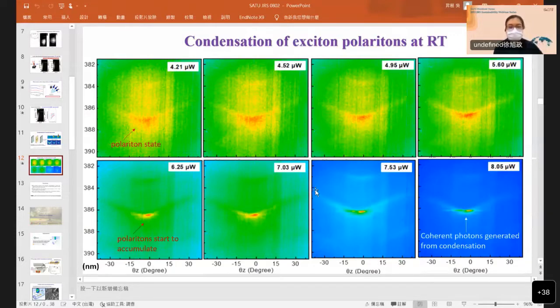So when you achieve the exciton polariton lasing, you can reduce the lasing threshold up to one or two orders of magnitude lower than the conventional one.